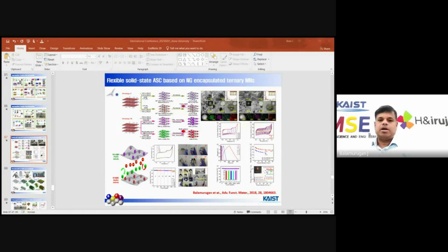But in the case of the conventional methodology, different kinds of metal nanoparticles are only absorbed on the graphitic networks. But in our method here, we make the core shell simultaneously, and we make the oxide to nitrate transformation because we use a cyanamide based material. You can see clearly metal nitride nanoparticles encapsulated by graphitic carbon networks in 2 layers.